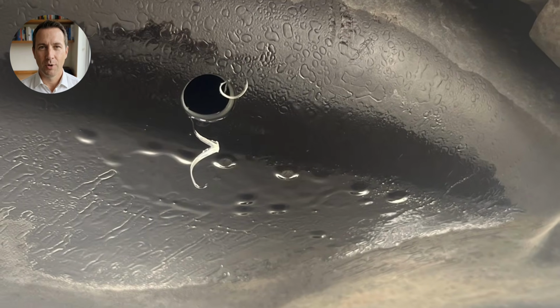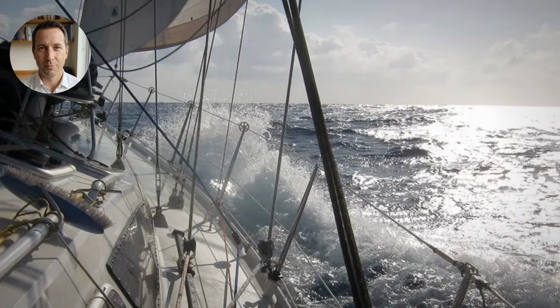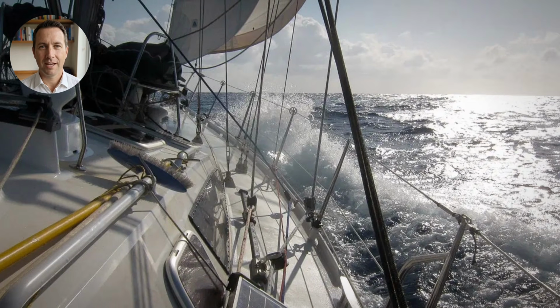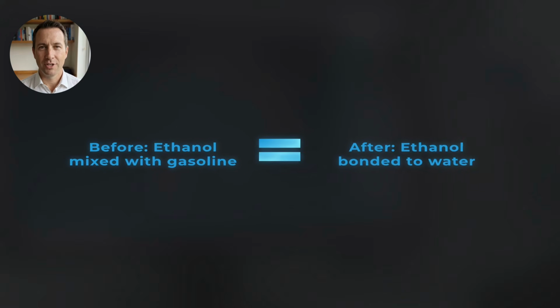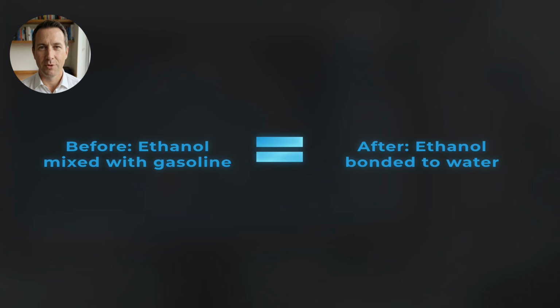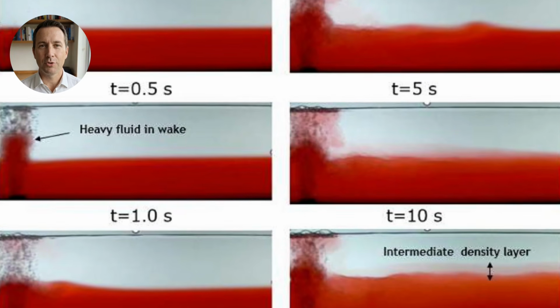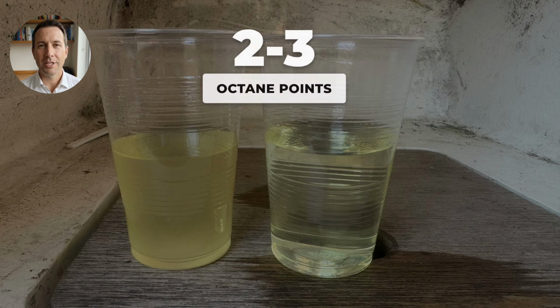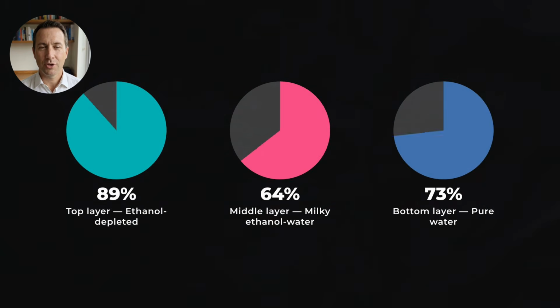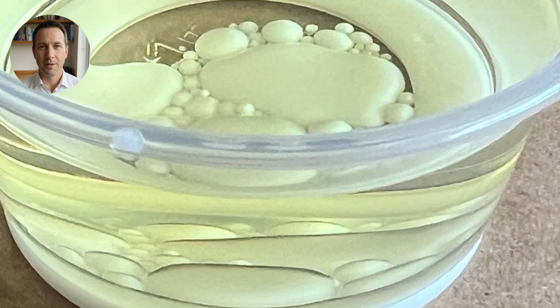That is a shockingly small amount when you consider that marine fuel tanks breathe humid salt air for months at a time. Once the water crosses that threshold, the ethanol stops bonding with the gasoline and bonds with the water instead. The fuel separates into 3 distinct layers. Ethanol-depleted gasoline floats on top, now running 2 to 3 octane points lower than what you paid for. A milky ethanol-water mixture settles in the middle, roughly 75% ethanol and 20% water. Pure water pools at the very bottom.